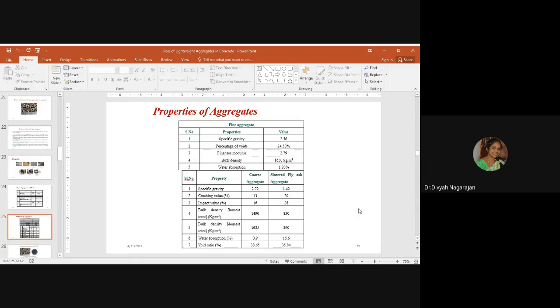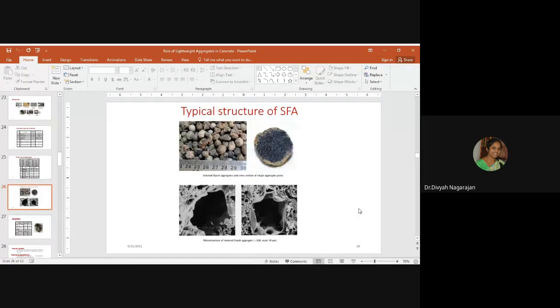Crushed angular aggregates develop good bonding with mortar paste. The strength of the bond between the aggregate and the cement paste depends upon the surface structure, surface roughness, and surface porosity of the aggregates. These sintered fly ash aggregates are rough and porous, with a large number of voids. This is the typical structure of sintered fly ash aggregate. When a sintered fly ash aggregate is broken down, the grain will look like this, and the microstructure is also shown here.